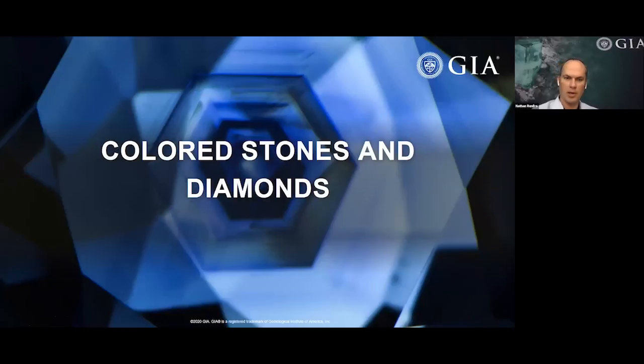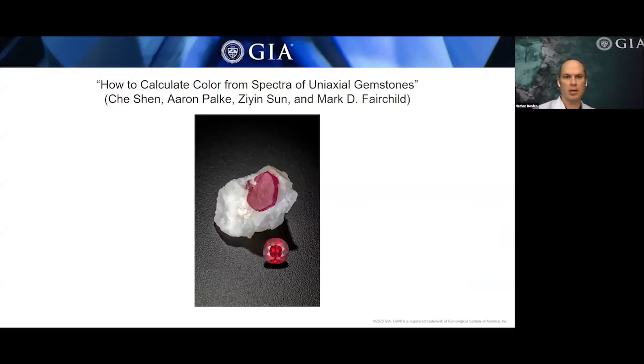All right, thanks, Chunhui. Okay, we're on to colored stones and diamonds for this issue of G&G. So I'll run through all the content that you can check out in more detail in the current issue. One of the main articles that we have here is how to calculate color from spectra of uniaxial gemstones by former GIA intern Che Shen and some colleagues there. And basically they developed a way to calculate color by using transmission spectra instead of absorption spectra, and are able to recombine the measured polarized spectra to predict the color that you'll get in a gemstone.